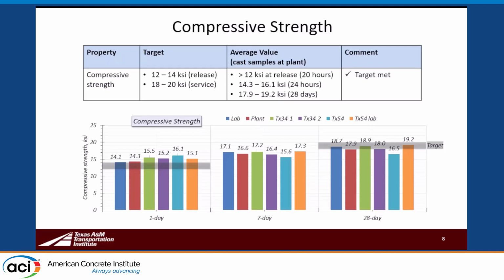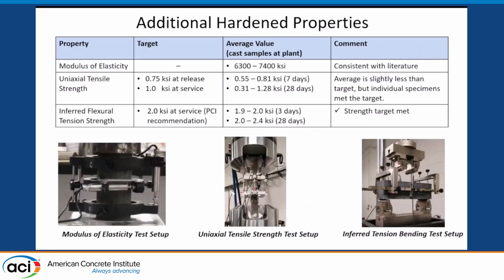And so with that, I can also mention that we had some additional hardened properties that we looked at, including elastic modulus. We did compare the values we got from the MOE testing and found that this is a little bit lower. It's not directly proportional to the square root of f'c like we have in the ACI code. As we get into UHPC, it's a little lower, but it is consistent with the literature. So we're in the range of 6,300 to 7,400 for our mixes, the various batches.